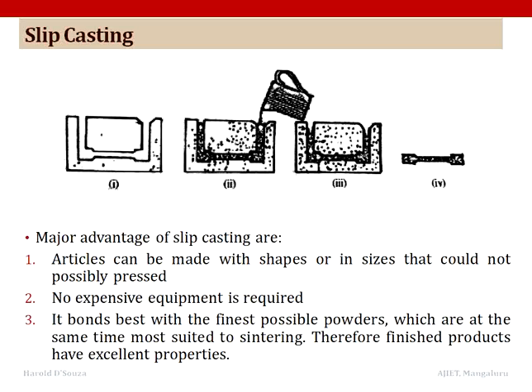The slip to be cast is taken in the form of a suspension of the metal powder in a suspending medium. The slip should have a low viscosity so that it can be readily poured. It should be stable during standing and have a low rate of settling. The slip cast shape should be readily removable from the mold. It should have a low shrinkage on drying and a high strength after drying. To achieve all these properties, fine powder particles which are less than 5 micrometer should be used.